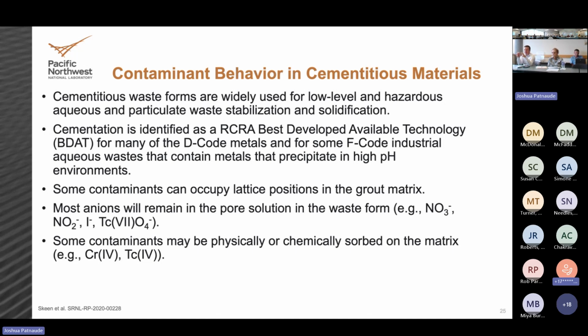So as you start to consume water and make those mineral networks, the pores that are left behind, those salts that are resulting from that dissolving liquid waste, they start to be present, concentrated in that pore space. And that's where the chemistry happens. So if we design a reducing environment into our waste form, within that small little pore structure, that's where the dissolved sulfur from the slag will interact with the chromium or technetium and do the reduction and precipitate it out.